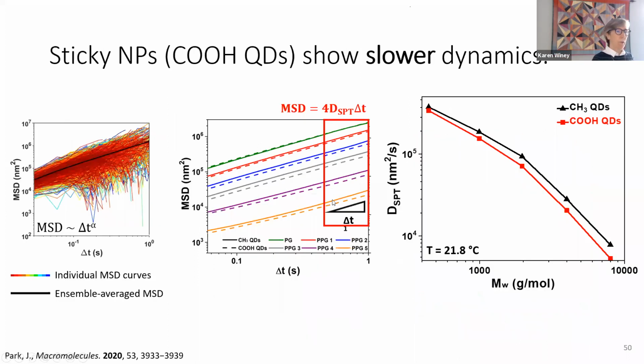Okay, single particle tracking. And then we can calculate the mean square displacement from all of those tracks. The colors are individual tracks, and then the black line is the average, the ensemble averaged. And then out here at like 1/2 to 1 second, we have diffusive behavior, and this is how we extract the diffusion coefficient from the single particle tracking experiment.